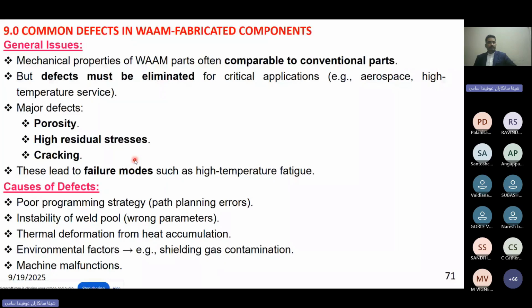Okay, then next one. What are the common defects we observe in the VAM technique? Basically, porosity is the main thing, especially in gas metal arc based VAM technique. More and more porosity will be formed. And if you are not properly choosing the parameters, more porosity and high residual stresses will be there. And whenever there is high residual stress, obviously there will be cracks. So whenever the VAM component has some porosity, residual stresses, and cracking, it will definitely affect the fatigue life of the component. These are some common issues.